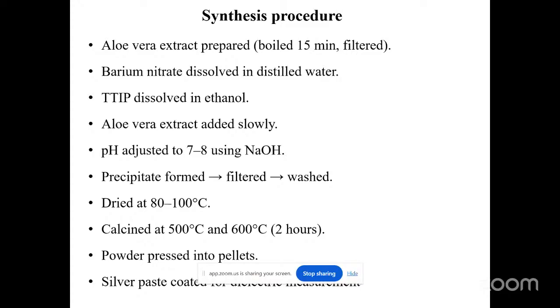First, aloe vera extract was prepared by boiling and filtering the plant gel. Barium nitrate was dissolved in distilled water and TTIP was dissolved in ethanol. Then aloe vera extract was slowly added and the pH was adjusted to around 7 to 8 using NaOH. A precipitate was formed which was filtered, washed and dried. Finally, the powder was calcined at 500 degrees Celsius and 600 degrees Celsius, pressed into pellets and coated with silver paste for dielectric measurement.